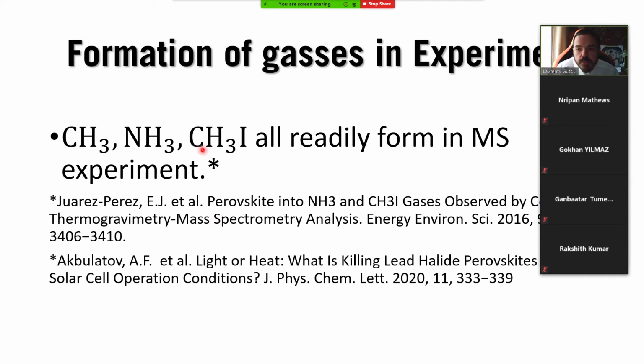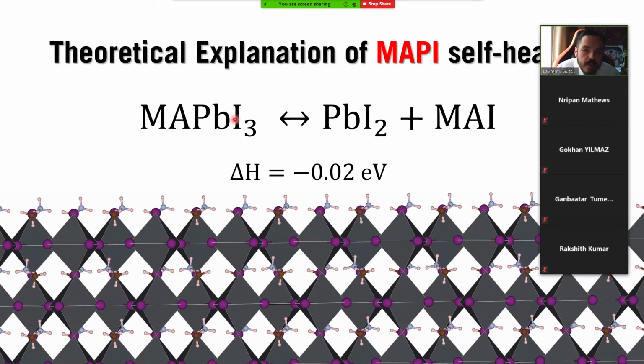Experiment previously showed that we have methyl, ammonia, and methyl iodide. They readily form in mass spec experiments, and of course mass spec is ionizing radiation, so that's something that we can look at to kind of figure it out. And of course, the main issue of methylammonium lead iodide is it separates into two phases: lead iodide and methylammonium iodide. And this one is the issue because this one of course is the one that can degrade to gaseous products.